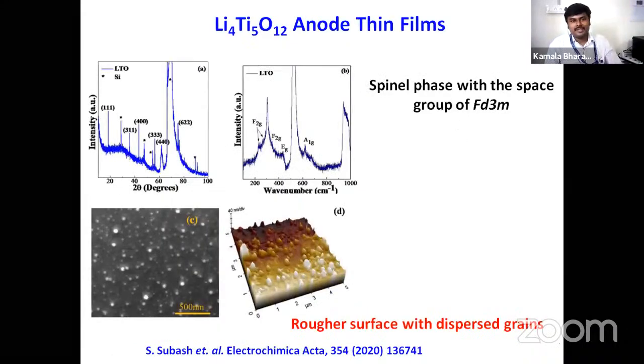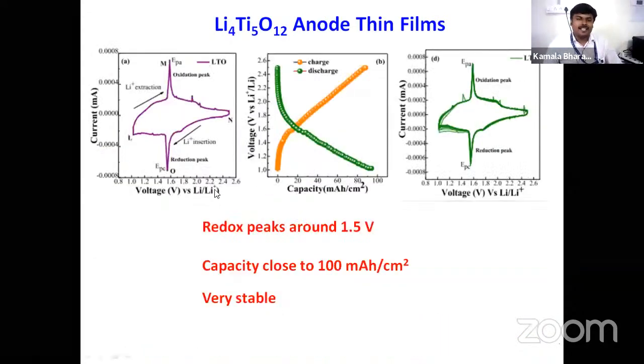Again, we prepare these films using sputtering technique. XRD and Raman confirms the formation of these films in spinel phase with space group of Fd3m, and morphology indicates a very rough surface with dispersed grains. And this is the electrochemical data of these thin films. You see here the CV curve exhibits the redox peak around 1.5 volt, which is again the fingerprint of this material, which confirms the formation of this film in the right phase.